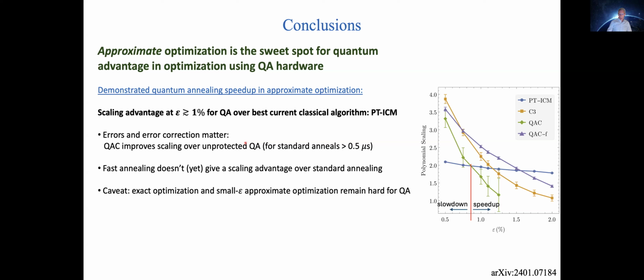I've also argued that errors and error correction really matter here. You see how QAC does better than the C3 strategy, which it certainly does better than not doing error correction at all. So we definitely need these error correction ideas here, which is not surprising given everything that we believe about scaling quantum computers. The fast anneals, they're doing okay. They're doing better than PT-ICM for sufficiently large values of the optimality gap. But they don't yet give an advantage over the standard anneals, comparing the QACF versus QAC. And that is probably because of the issue of the non-optimal annealing schedules, if I had to guess.